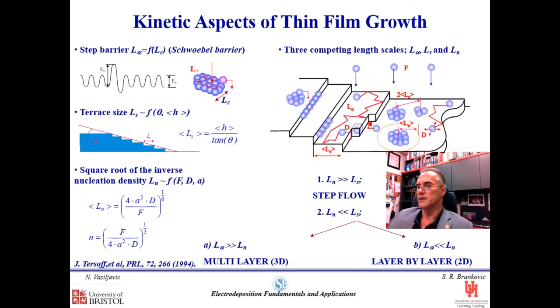When we talk about kinetics of the nucleation or kinetics of the growth, we are not talking about nucleation rate anymore, we're talking about nucleation density. To elaborate a little bit further on this, I will explain that the growth modes, when we consider kinetics of thin film growth, are not defined in terms of thermodynamic values, but rather in terms of three different length scales that are mutually competing and whose mutual relation defines the growth mode.